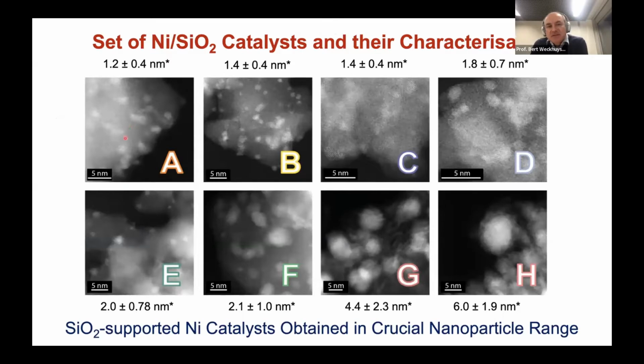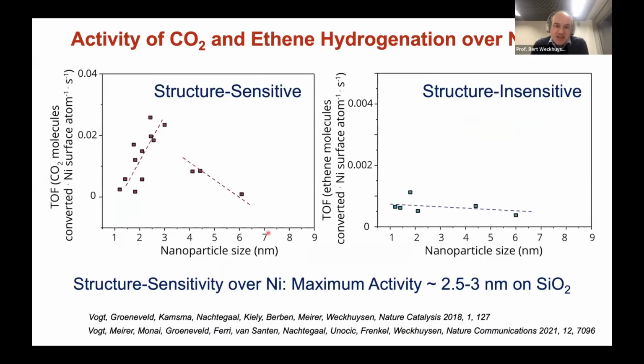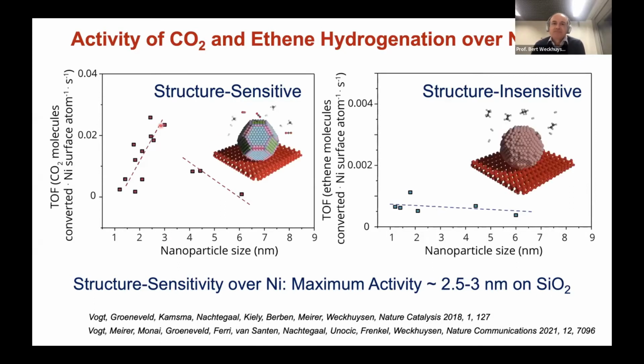For this, we have been studying a wide variety of nickel silica catalysts, nickel nanoparticles, which differ in their metal nanoparticle dimensions. And by doing so, we can change the activity by changing the nanoparticle. Here I show you CO2 molecules converted per nickel surface. And we can do that for CO2 hydrogenation or ethylene hydrogenation. CO2 hydrogenation has a maximum, and ethylene hydrogenation has not. We call this structure sensitive. We call this structure insensitive. And somehow you have a maximum around 2, 3 nanometers. So here somehow facets are dominating. Here seemingly facets are not dominating.